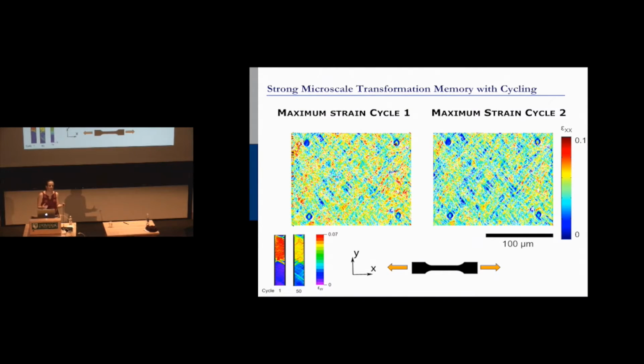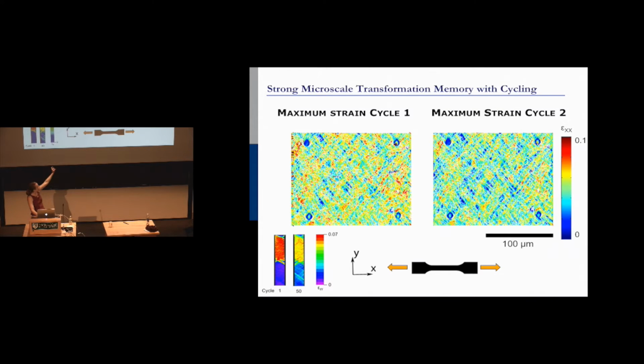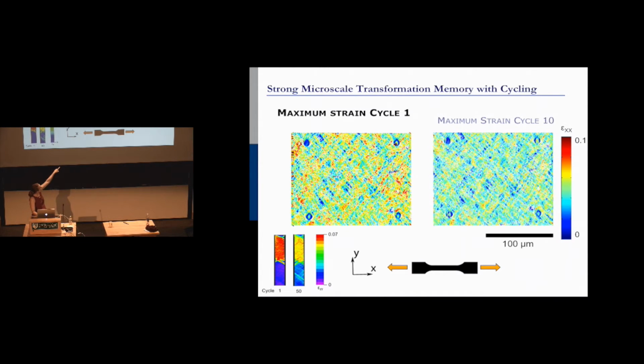The shifting is just due to the fact that we have this specimen in a stage. We do our best to keep it centered, but there's going to be some natural shifting of the specimen as we load and unload. But what's really crazy is the pattern is so faithful, right? You look at this. This literally looks like I took it and just shifted it around, but these are actually load and unload cycles, and it's forming the exact same way every time. Very, very similar. So there's a very strong dislocation network that lays down. There's a very strong network of, we think, residual martensite that's laying down that's causing this to form in the exact same way over and over again, very faithfully.